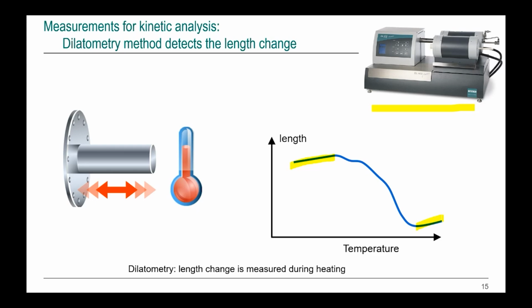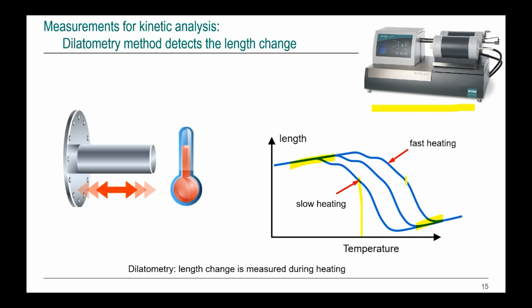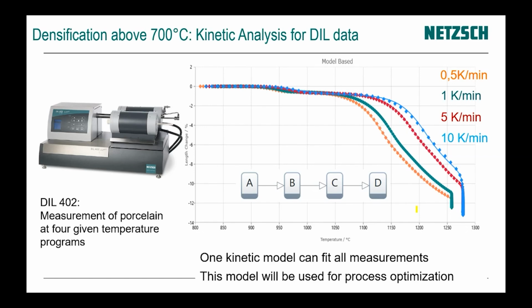Again, we have some temperature points where everything happens. And again, the same as it was during decomposition. Here, the result depends on the heating rate, how fast we make heating during the sintering process. For slow heating, everything happens at lower temperature, and for fast heating, our sintering, our shrinkage happens at higher temperature. And again, we can take our real data. Here, the thermal expansion is already removed. We have step number 1, step number 2, step number 3. We create a 3-step reaction.